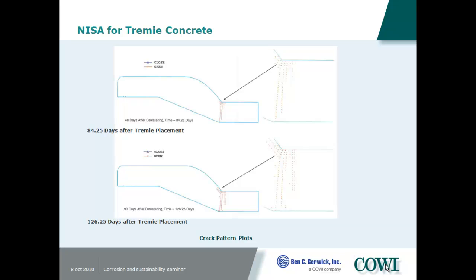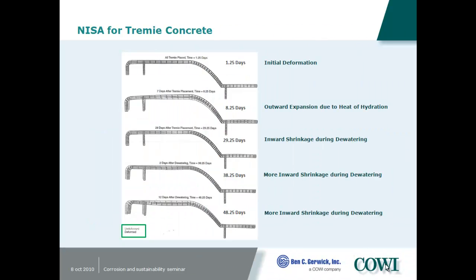But the Army Corps wanted us to try to characterize the widths of the cracks and whether they'd be opening or closing if they did form, and how fine they'd be. So we did do that analysis. And also they wanted to see the deformed shape of the shell as it was expanding and contracting with time. So we had that, including the natural shrinkage that was going on too. So it's not just thermal, it's also, as concrete hydrates, there's a chemical shrinkage. Of course, since it's underwater, there's no drying shrinkage going on.